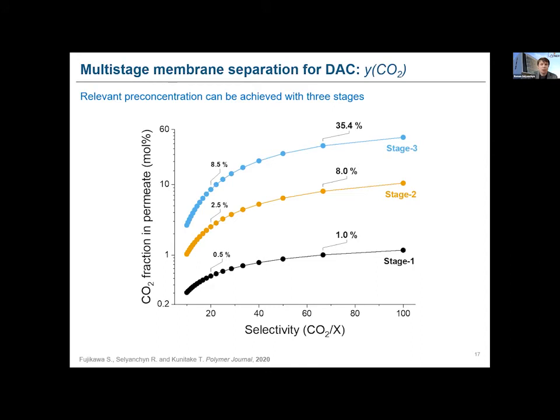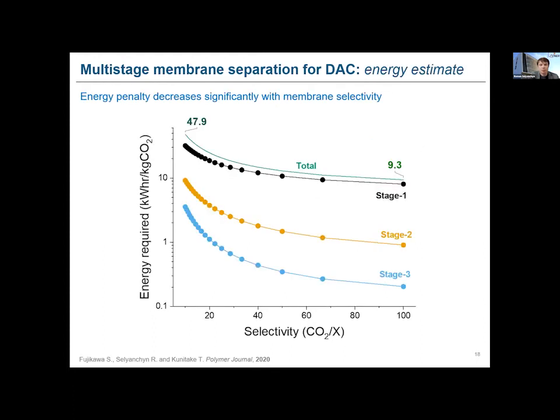And on this plot, you can see the dependence of the concentration in the product of each stage, because we have 3 stages, stage 1, stage 2, stage 3, how the concentration of gas changes when it passes through the membrane. As you can see, it's only 1% when it passes one stage of membrane, which is obviously not enough for any type of chemical transformation. But after 3 stages, the concentration becomes relevant, and after communication with electrochemistry people, we understood that this would be a sufficiently concentrated feed in order to use this stream for chemical transformation of the carbon dioxide.